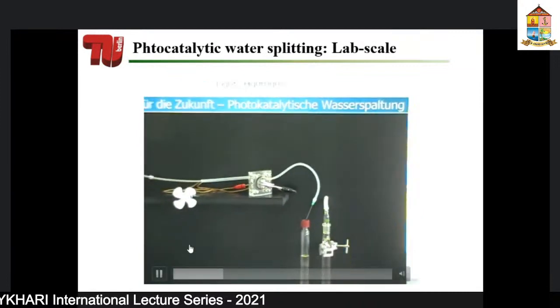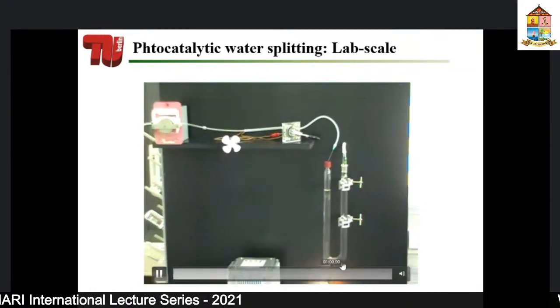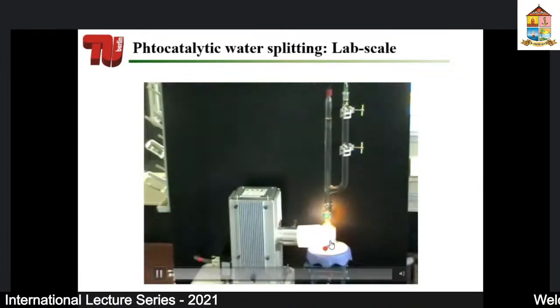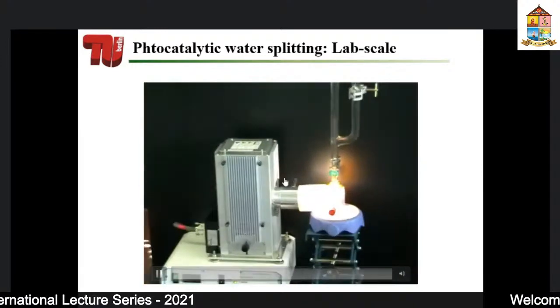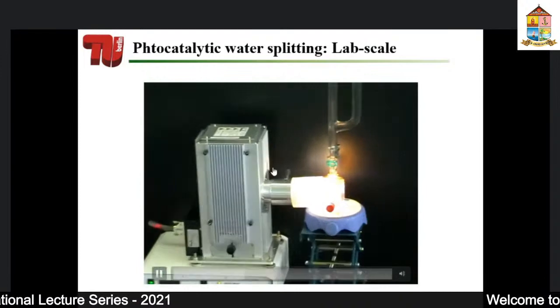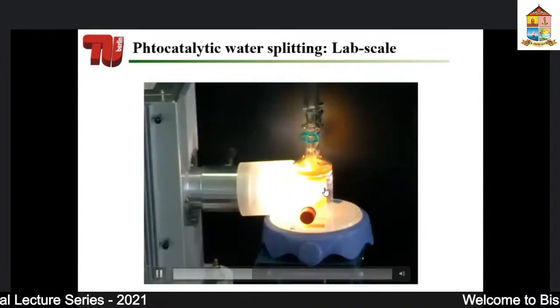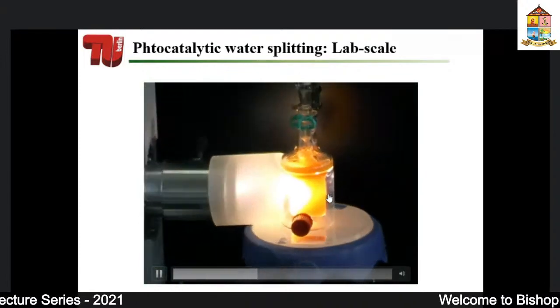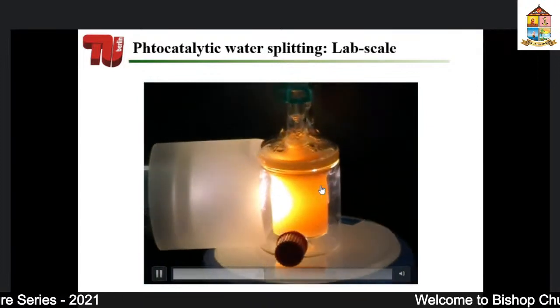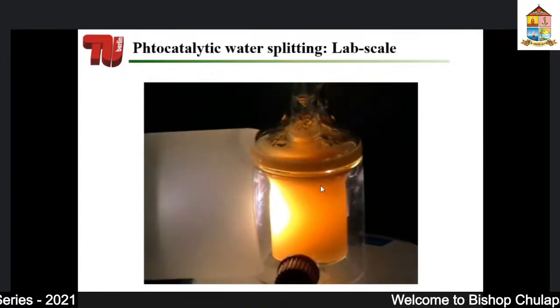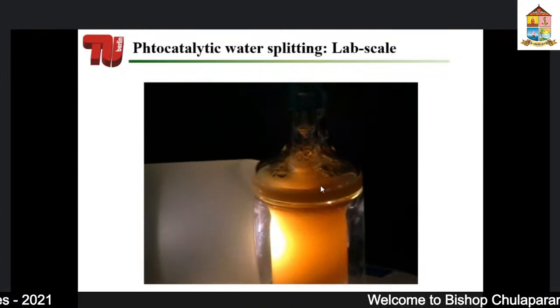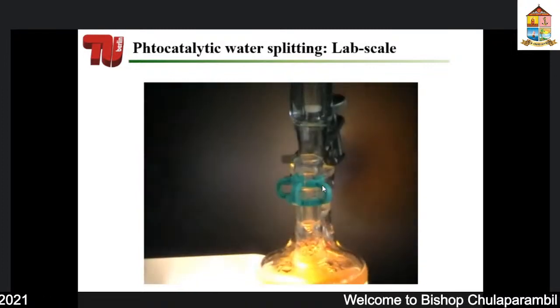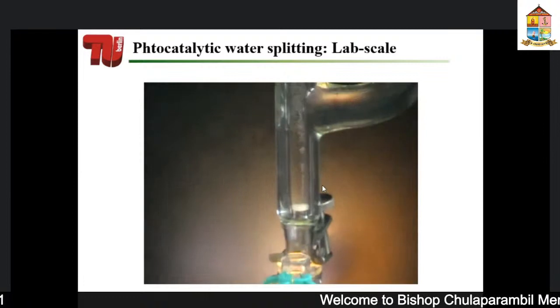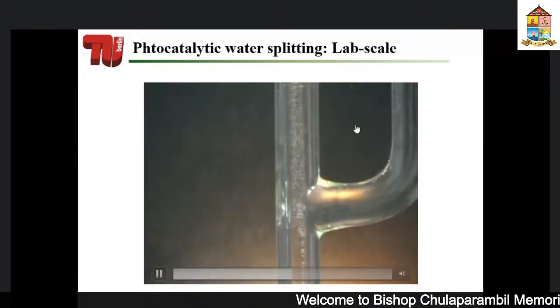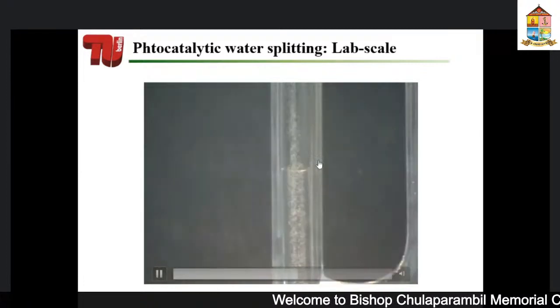As you could see, we have kept our carbon nitride material in this vessel, or in this reactor, and this is the simulated sunlight which we focus on the material, and your material is getting stirred at the same time so that it can have a maximum exposure to the sunlight, or simulated sunlight. And what you would see here is the generation of hydrogen. Slowly you can see these bubbles, and they will be collected on the top of the reactor.